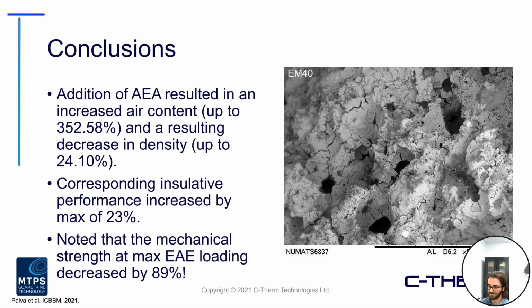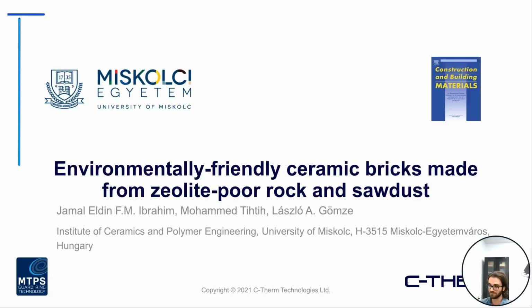And as a note, they did find that at that maximum loading, because of the structural aspects, the highest loading did decrease the overall mechanical strength by 89%. So of course, there are various aspects you need to consider when developing these types of materials. We're obviously focused on the conductivity side of things, but there are a variety of other variables that need to be taken into account as well.